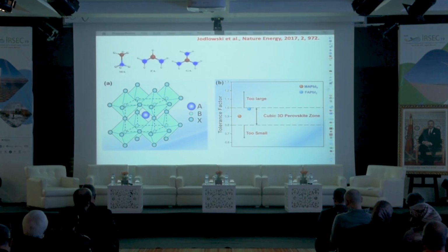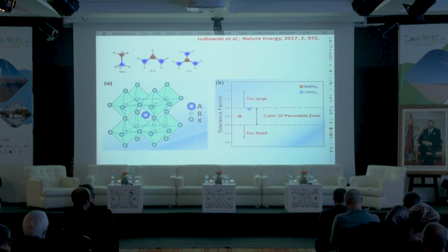So the increased hydrogen bonding is very important. From methylammonium to formamidinium, you have 2 NH2 groups. From formamidinium to guanidinium, you have 3 NH2 groups. So the number of NH2 groups enhances your hydrogen bonding, and that should significantly enhance your stability.